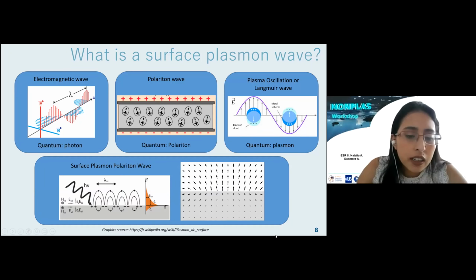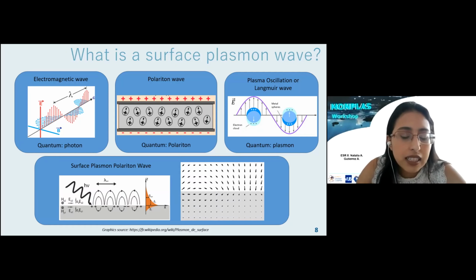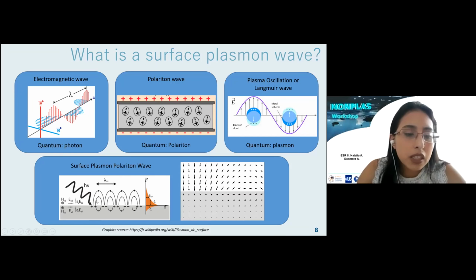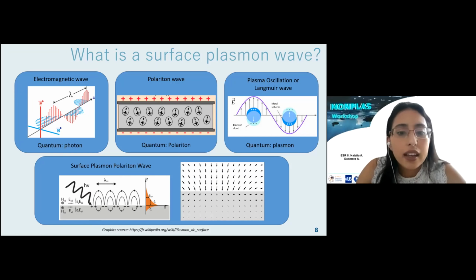This occurs in an interface between a metal and a dielectric. So what happens is that light is absorbed by the electrical charges inside the metal, and this will generate a plasma oscillation, and the displacement of the electrical charges of the plasma oscillation will generate an electrical field inside the dielectric medium, which will also cause a polariton wave, as we can observe here in the graphic.